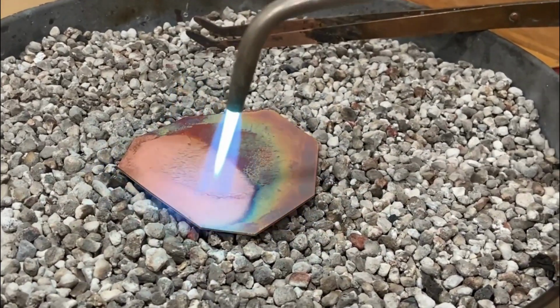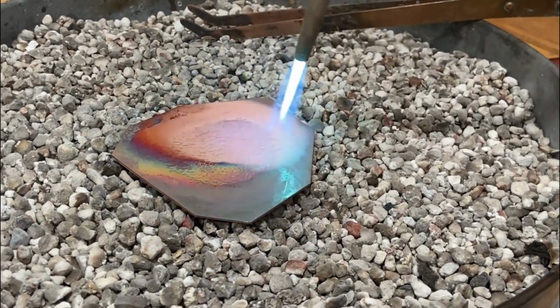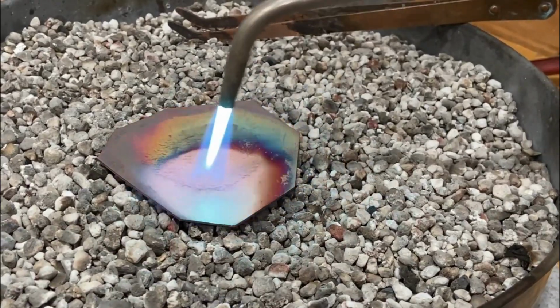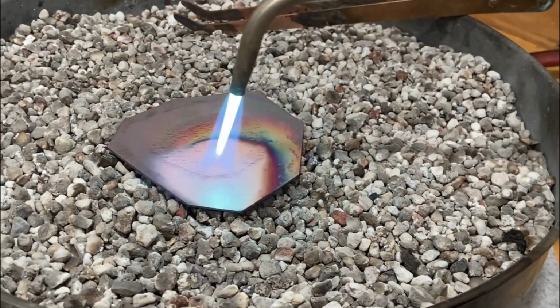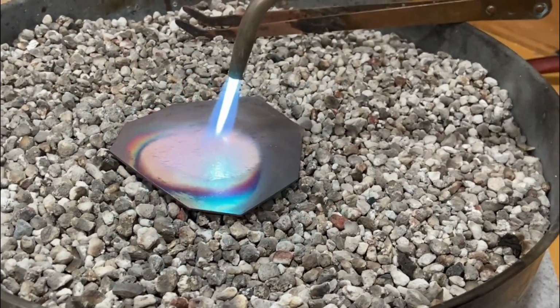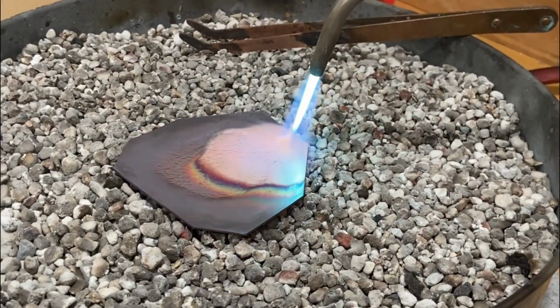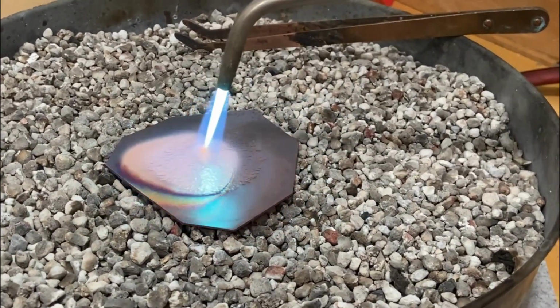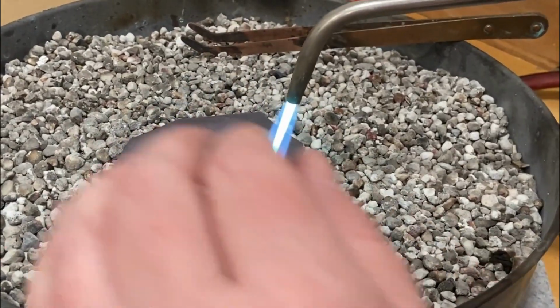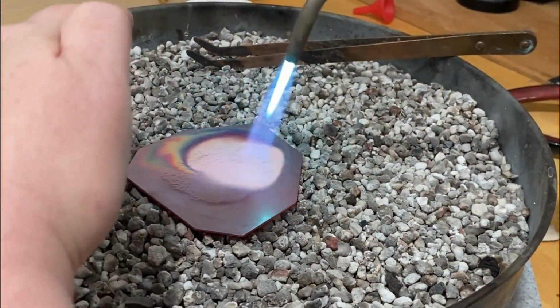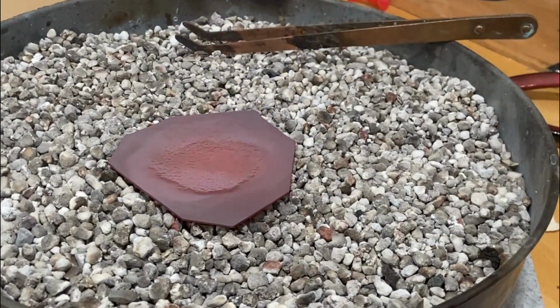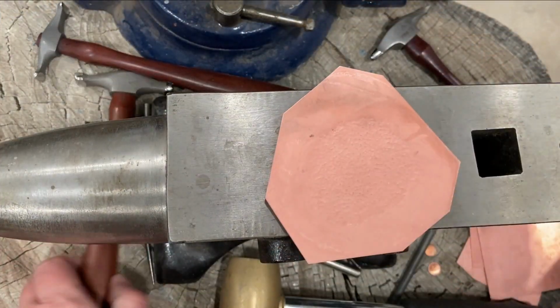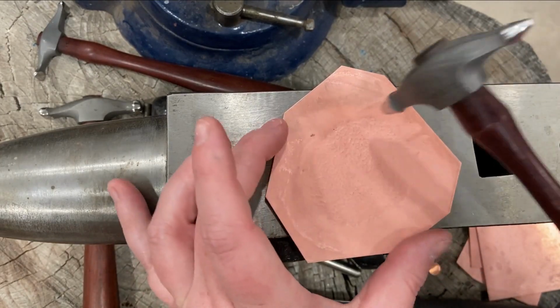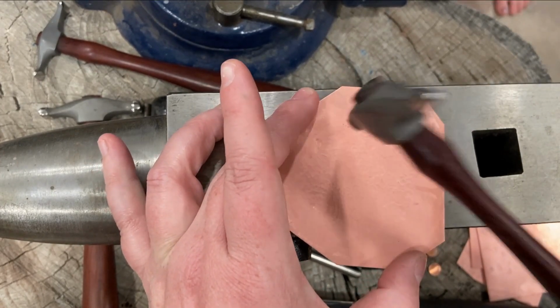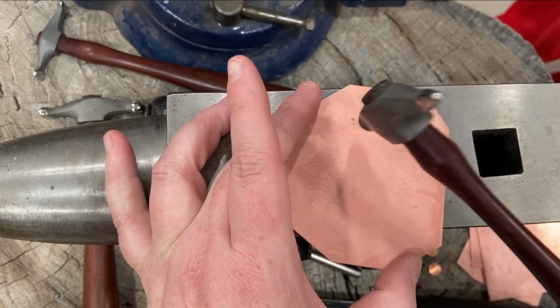And you don't want to be fooled by the surface color that happens as the metal heat patinas. You want to heat it beyond that surface coloration until the metal is actually glowing from heat. So here I'm getting pretty close. You can see as I move the torch away, there's a red glow. If you shade it a little bit with your hand, you can see it better. And then I'm going to pickle and clean it and come back. And then I'll just start where I left off.